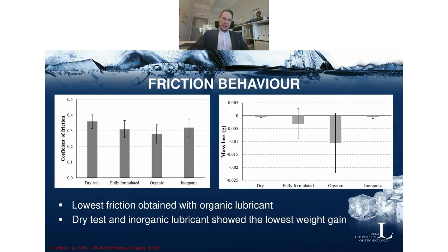So what did we find here? Well, on the left side, you can see the coefficient of friction, the average coefficient of friction from the steady state part of the test. You have 4 different configurations. You have dry testing as a reference to the left, followed by the fully formulated, and then the organic and the inorganic lubricants. So it's quite clear that the organic shows the lowest friction, and the inorganic and fully formulated are more or less the same, and a little bit higher for the dry test. So it seems like the organic part of the lubricant is what provides a friction reduction. Interestingly, not to an extent that it actually reduces the fully formulated lubricant to a level of the organic. So the organic alone is actually better in that case.